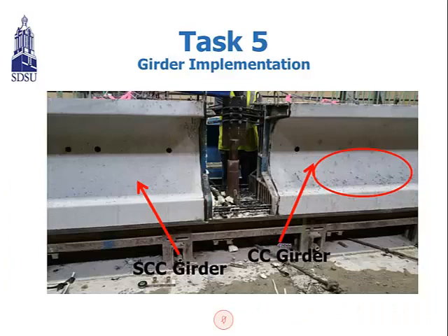And once it was done, we inspected the surface of the SCC girder and the CC girder. As you can remember, the SCC girder takes only a few minutes and doesn't require any vibrator, while the CC concrete requires using the vibrator so the cement goes smoothly down to the bottom of the form. And also once we inspected the girder, there were some bug holes on the CC girder. On the other hand, there are no visible bug holes in the SCC girders.